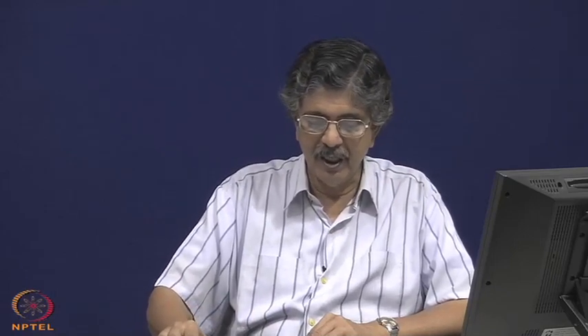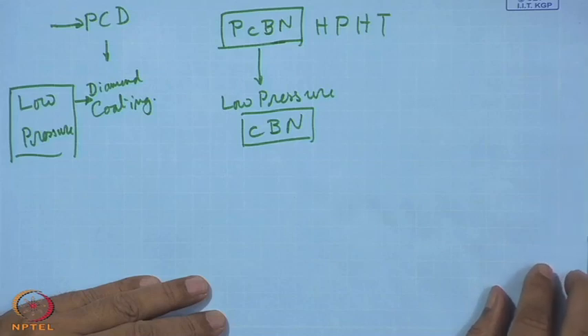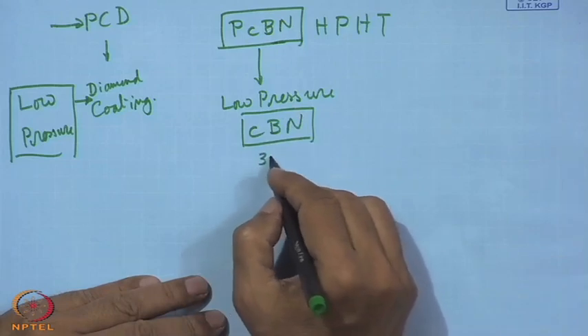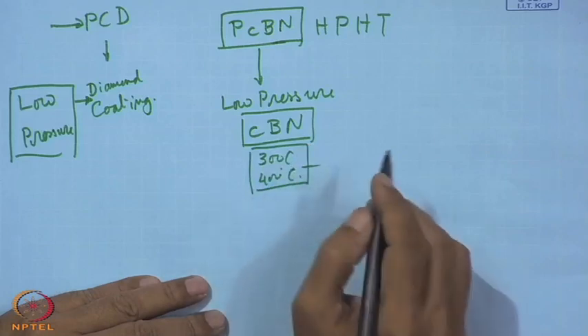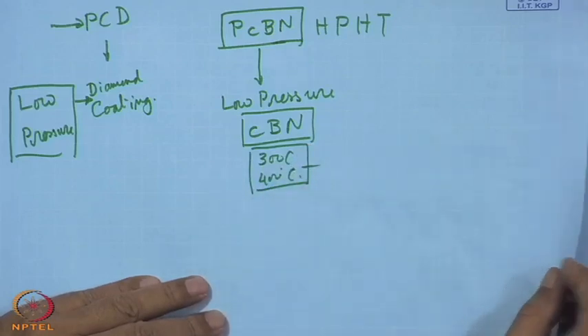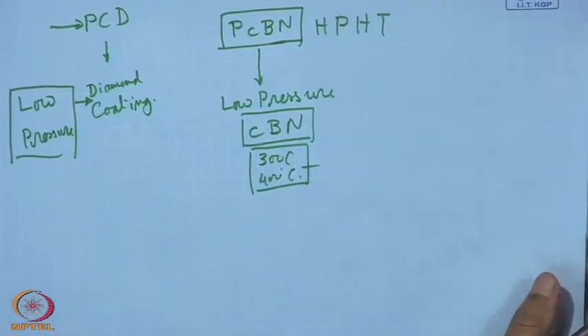With this available coating, the user has much more flexibility. This coating can be put on various complex geometry cutting tools — even end mill cutters with CBN coating. This is the result of low pressure, low temperature synthesis that can be handled at around 300 to 400 degrees centigrade. That is the specialty of this process.